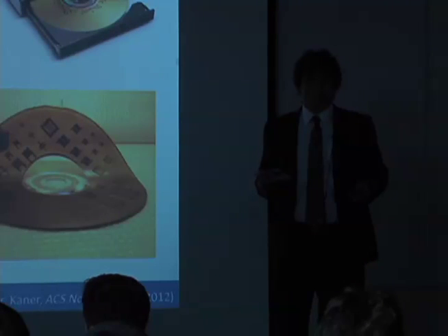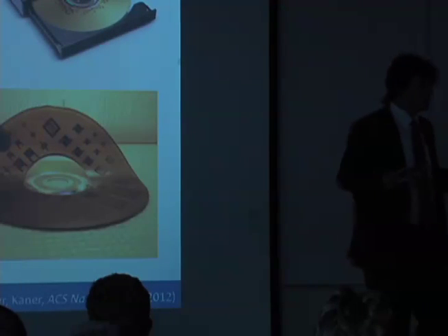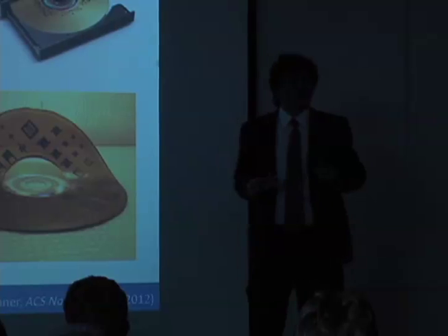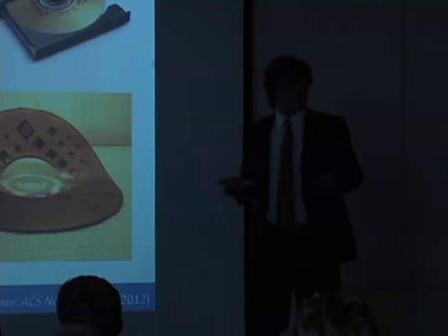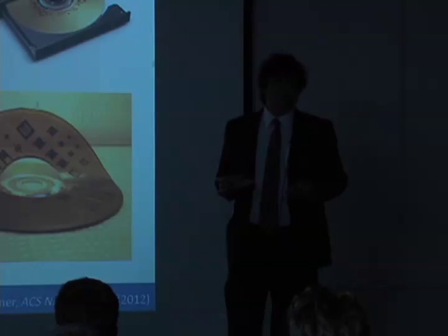And the problem with conducting polymers is unlike other polymers, you know, if you look around you, the chair you're sitting on, the carpet, your clothes, they're all polymers. Yet you probably would be hard-pressed to name an application for conducting polymers. Some of you might because there's a lot of work out here. But most people can't. The reason everything's polymers around us is two reasons. One is polymers are cheap, but the other thing is they're processable. You can melt them and make objects out of them, or you can dissolve them and coat them. Conducting polymers don't do either.